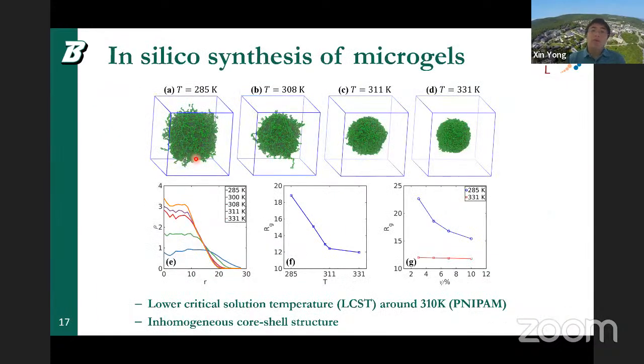So first of all, we want to create microgels in the simulation. So here we use our previously developed in silico emulsion polymerization technique to create the microgel. So basically here we actually model the polymerization in the presence of 5% cross-linkers within a droplet, within an emulsion droplet. And then this method allows us to create a microgel with more realistic network structure. In particular, an inhomogeneous core-shell structure.